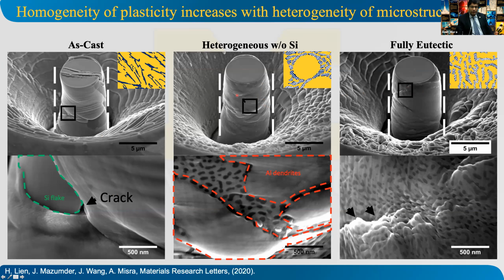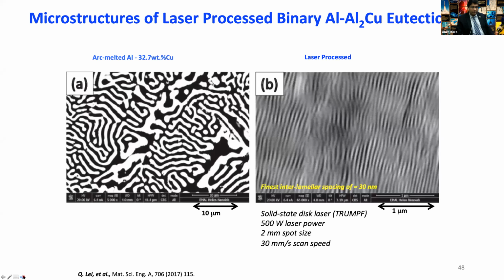In the case of these heterogeneous, you see some signs of where on the surface you have the aluminum dendrites, those are deforming more, so they see some extrusion on the surface there. But generally for the fully eutectic, the homogeneity of plasticity increases with the heterogeneity of microstructure. So that's the punchline of this, and that's the surprising behavior, that by making the structure more heterogeneous, we are making plastic flow more homogeneous at very high strength levels.